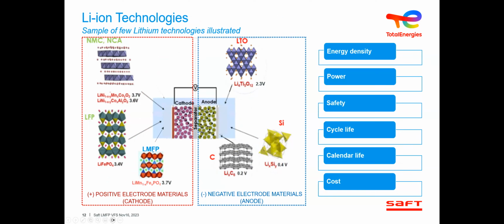Like I mentioned, the LTO with no solid electrolyte interface, or the silicon anode that has very high interaction with lithium, or the carbon structure on the anode side. On the cathode side, you choose laminar structures like the NMC or NCA, or iron phosphates, or lithium manganese phosphates, which are different. They offer different structures. These two are what we call olivine structure or tubular structure. So they form tubes onto which the lithium embeds itself. But the phosphate stabilizes the electrodes. This is where the safety gets improved from. Instead of having a laminar structure that can collapse and create not necessarily stable compounds.